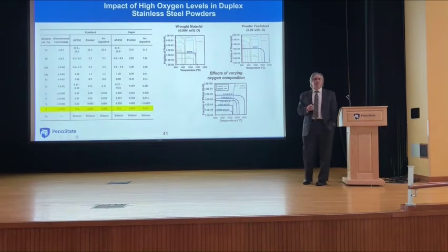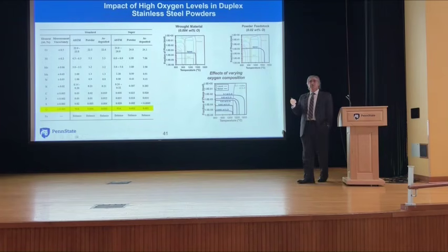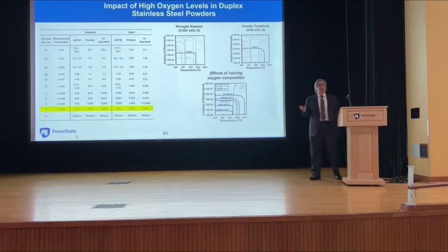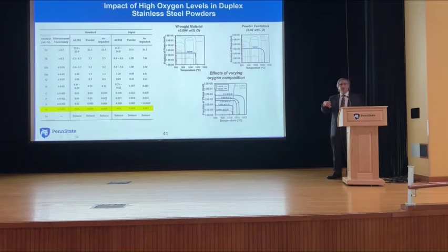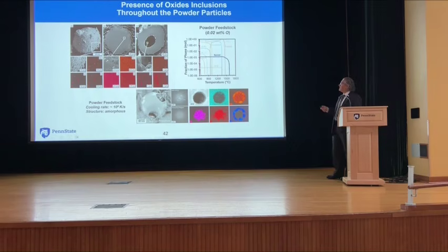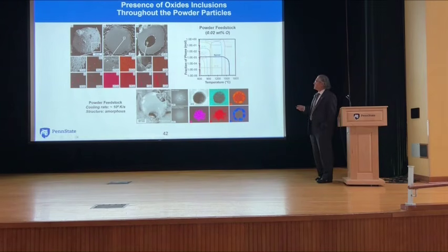Chemical engineers have a little statement that they make. Dilution is the solution. And what that means is, how do I get rid of it? I add more iron to it. So I need to dilute it and make that amount smaller. We do that with copper all the time in steels. In order to get the copper levels down in the scrap stream, you just add more iron, you add direct reduced iron. But what you start to see here is you can start forming a lot of oxides, and they appear in the powders, and even so people say, oh, it's just on the outside of the powder. Nope.